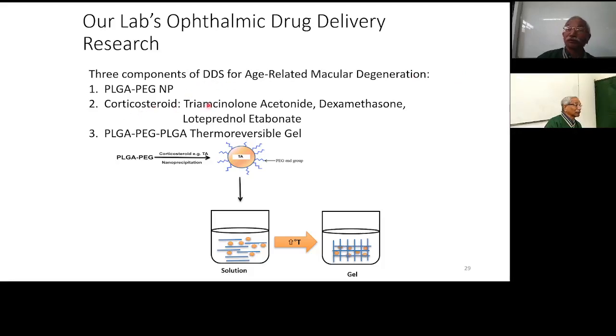So we use corticosteroids, which remove the inflammation in the eye. They are all anti-inflammatory drugs: triamcinolone acetonide, dexamethasone, and loteprednol etabonate. These are the three drugs we tried. These are used for macular degeneration, but not as nanoparticles. We tried to put them into the PLGA-PEG-PLGA thermoreversible gel. Thermoreversible gel becomes gel if the temperature is up, and becomes solution if the temperature is low. That is called thermoreversible. The gel-sol formation is dependent on the temperature.